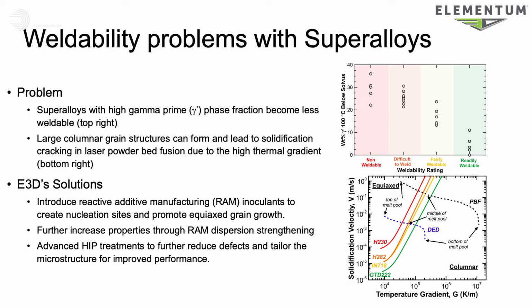There's multiple approaches you can do, and one of the ones that's been traditionally investigated is using hot isostatic pressing to heal up the internal cracking and defects that can develop during printing of these alloys. And there's been a lot of success with this approach. You can heal up most of these internal cracks and provide great performance improvements for these alloys that are susceptible to such defects. Now, there's some challenges with that though too, in that while you can heal up the internal cracks, any surface cracks that are open, those won't benefit from the HIP process. And so you have to deal with those a different way.